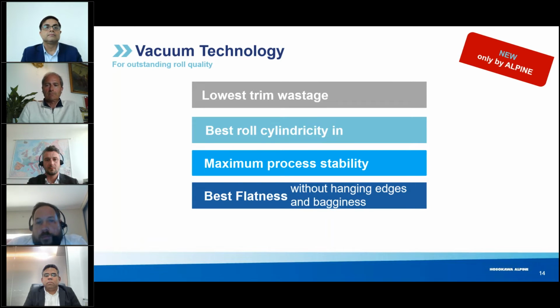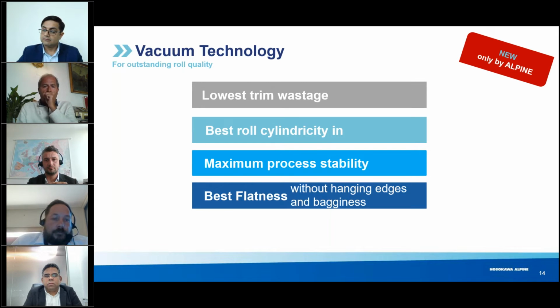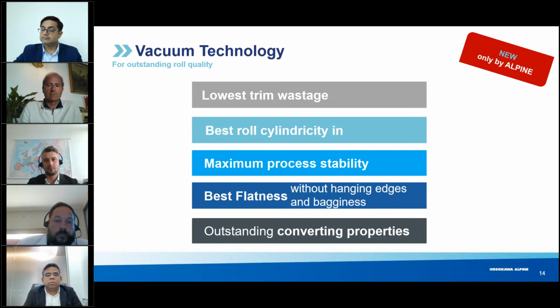So preventing the neck-in will lead to a lower trim wastage. The vacuum roller will help you to get the best roll cylindricity and the maximum process stability because of the prevention of the web breaks. And this will lead to the best flatness, which is very important for the converting of the film, for example, like we've heard before, for metallizing. This will lead to outstanding converting properties and is mandatory to produce a sustainable packaging solution.